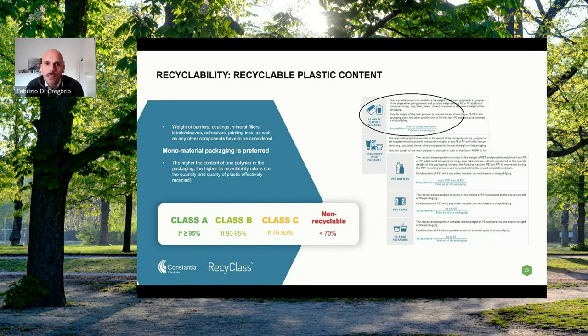Because I would like to remind you that when we're talking about recycling, we're talking about the recycling of the target polymer. For example, in the case of polypropylene films, with the RecyClass approach the first step is to count one by one all the substances coming from, for example, the laminating adhesives, the printing inks, the coatings, the barriers, and so on, to check at the end of the day what is the minimum threshold of maximum recyclable plastics in the packaging. And we have defined class A, class B, class C, and so on, with thresholds respectively of 95, 90, and between 70 and 90%.